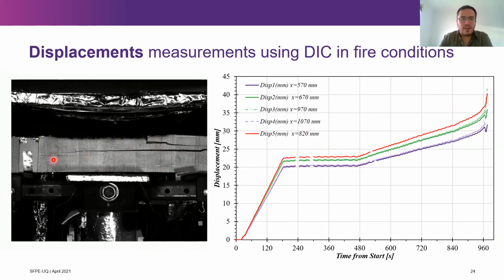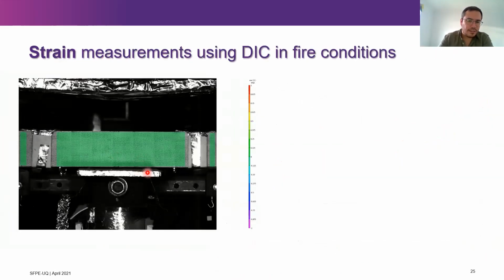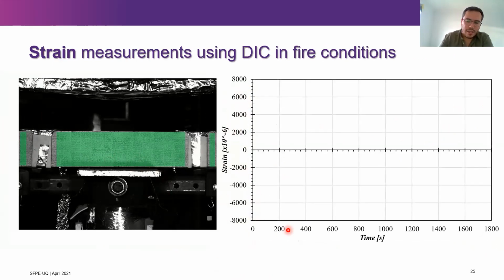The DIC not only allows us to capture the deflections, but it also allows us to capture the stress and the strain in the beam. So what you will see here is, again, strain against time. You will have tensions here, compressions here, and you will see the strain at 3 points. At the bottom of the beam, the furthermost fiber, we have compression in this case, because remember that we are loading upwards. So you're going to have the opposite of what you normally have in a conventional test setup: compression at the bottom and tension at the top.